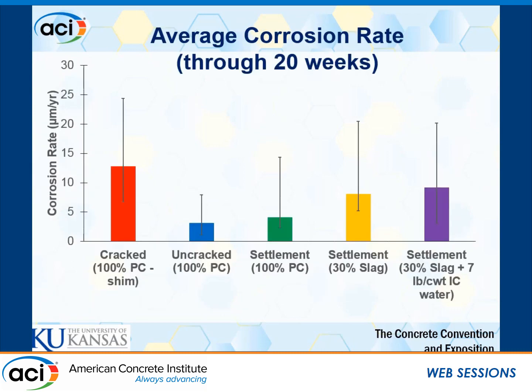And now getting into a discussion of corrosion rate. This is the average between corrosion initiation and the end of 20 weeks. So for our crack beam specimens, we have the highest average rate. That kind of makes sense: wide cracks, direct access for chlorides on that reinforcing bar. We see an average of about 12 or 13 micrometers per year of corrosion rate there.